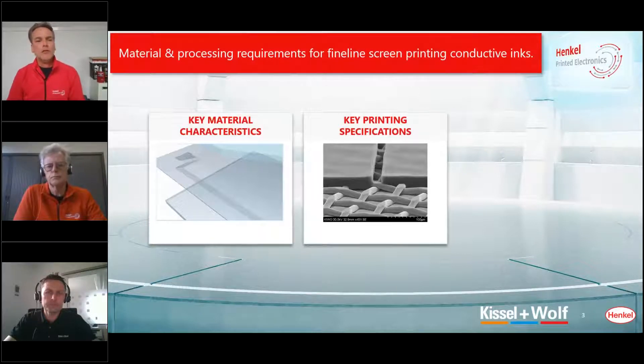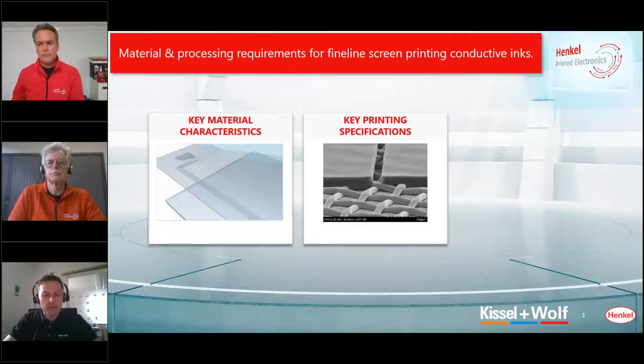What do you consider most important, Andreas? The mesh is of course important, and so is the emulsion — but where are the limits? Nowadays we have very fine meshes available: for example, 380 threads per inch with a 14 micron thread diameter. This is a really fine mesh available today. But to be honest, it gives also limits. From our point of view, it ends up at 20 microns. With Hans, maybe you also agree that 20 microns is really a challenge for the particle size within the pastes. Then screens get finer and emulsions perform better, and it will be possible to reduce below that 20 microns.